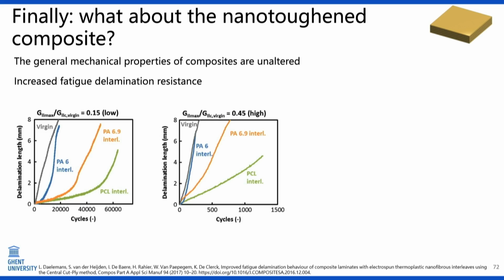Therefore, we produced composites as they would be used in industry, different layers stacked on top of each other, all with nanofibers in between them. First of all, the general mechanical properties, such as the modulus, were not decreased and were nicely retained. We didn't damage anything, and we didn't increase the weight substantially. But then, in fatigue, composites suffer from delamination, and we could see that during fatigue we have an increased delamination resistance. So this is the virgin composite.